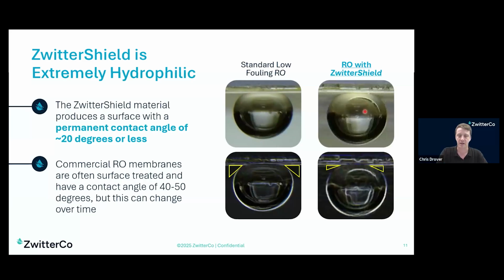You contrast that with the image on the right with the membrane that has ZwitterShield. Notice that the air contact area is quite a bit smaller, and the water has actually pinched in pretty far, trying to maintain as much surface contact with the membrane as it can. And this is due to that really hydrophilic surface.